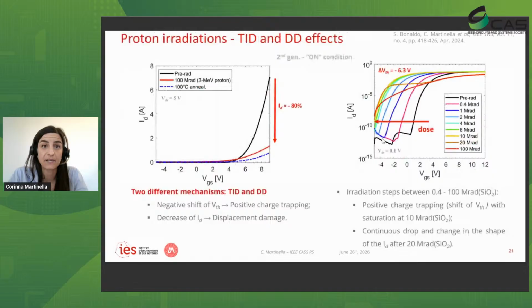Similarly, we did the experiments with the protons, and now we not only have total ionizing dose effect, we also have displacement damage. And so you can clearly see that even though we had a shift of the threshold voltage, by the end of the irradiation, we have a drop from the black line to the red one of about 80% of the current of the component.